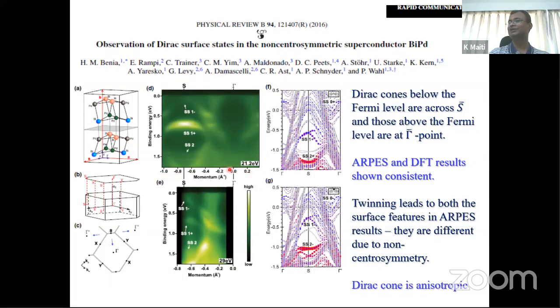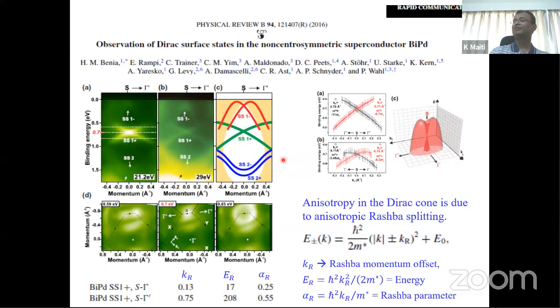So the gamma point is here. And they have actually justified by calculations that the Dirac states are not at the gamma point. But of course, these are surface states that they have shown. And they find that this Dirac cone that you observe here has significant anisotropy. Anisotropy means that this is the S point, which is the high symmetry point, and if you plot along the S-gamma and S-gamma prime directions, they are different.